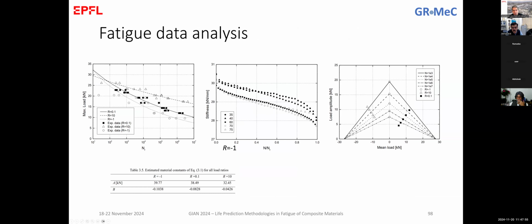So we did also the fatigue data analysis. Again, I repeat, plots that are relevant to any other type of material, stiffness degradation that is similar to other types of material, and then the constant life diagrams. Here we see that the typical Goodman diagram shown here is not valid for this material. It underestimates the behavior in compression and overestimates the behavior in tension.